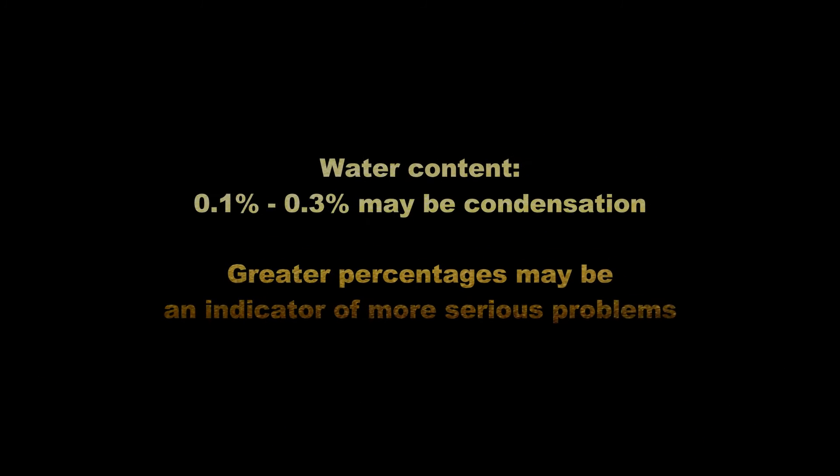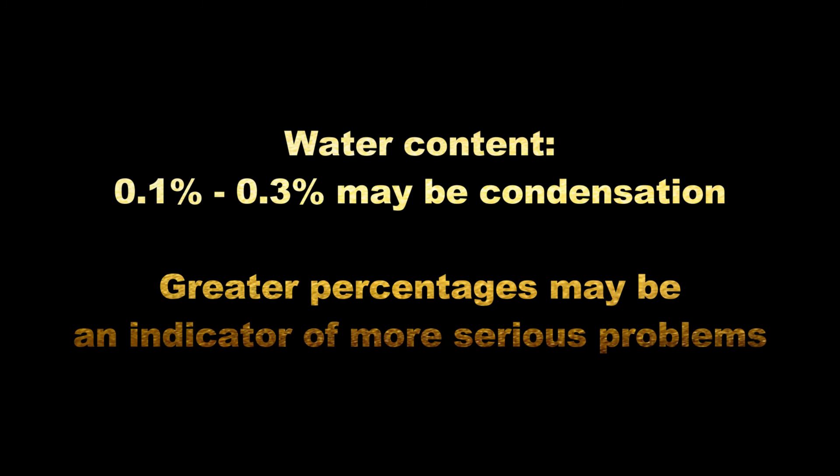Water content will also be reported by percent volume. Values of 0.1% to 0.3% are commonly the results of condensation. Values exceeding this amount could also indicate an accumulation of condensation, particularly in vehicles which frequently do not reach their maximum operating temperature before being shut down, or could be an indicator of a more serious issue such as coolant intrusion.